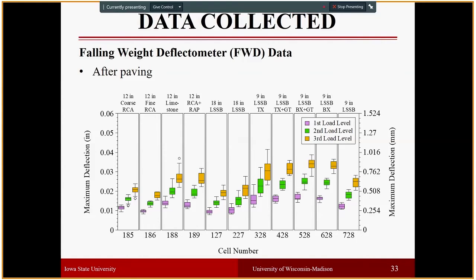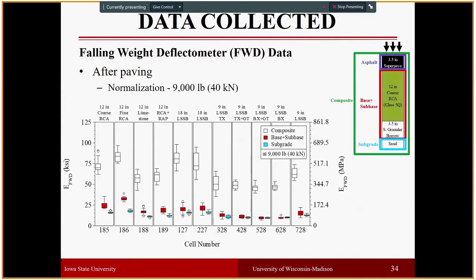After paving, before any traffic load was applied or few traffic loads were applied, we analyze the falling weight deflectometer data again, and then we look at again the third load both for composite and layered analysis. The fine RCA and coarse aggregates by far showed the highest stiffness, and after paved, the thicker large stone subbase test sections performed almost equal and made better than coarse RCA and equal to fine RCA test sections. And class 6 limestone test section and RCA rep test sections had almost identical stiffness to the large stone subbases built with geosynthetics. So when unbound stiffness analysis, these large stone subbase test sections with geosynthetics perform a little bit lower, but once the road is paved, they kind of bounce their performance in a higher level.